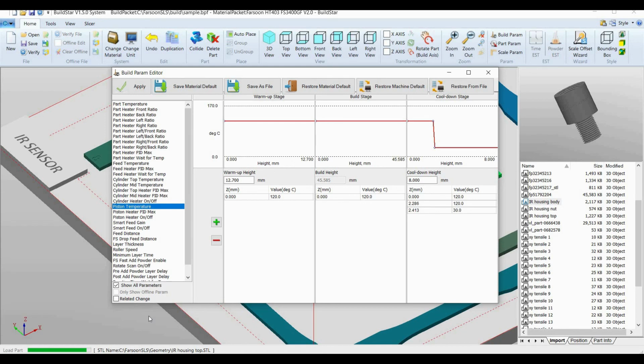Lastly, we have piston heater temperature. This is going to be the heat source at the bottom of the build. You want to retain and maintain the heat not only at the bottom but in the middle and at the top. That's why we have heaters on the sides, on the bottom, and then the part temperature heater. So to change that, if you see that you have parts at the bottom of the build that have warped post-build, then usually your part piston temperature is too low. To change that, it's the same way. Go into part parameters or build parameters, and you go into your build and change your temperature that way.